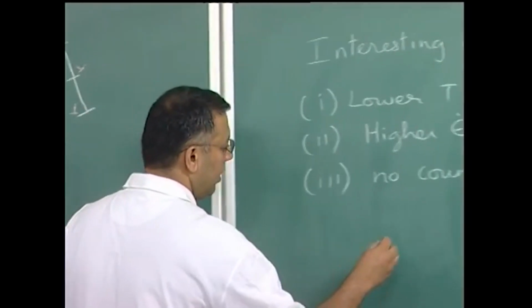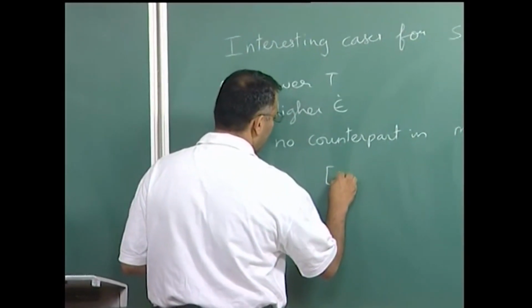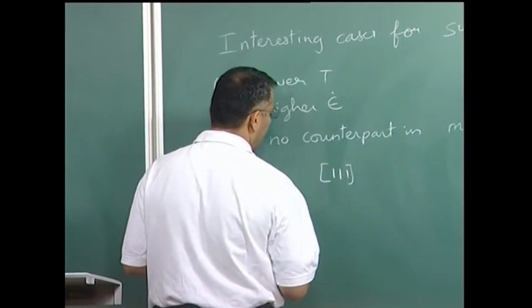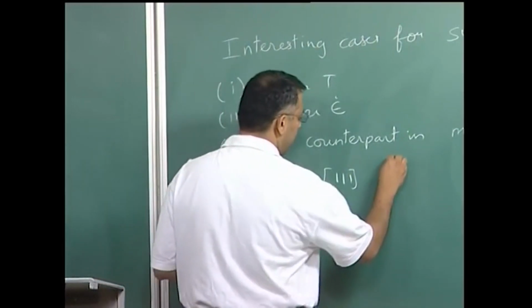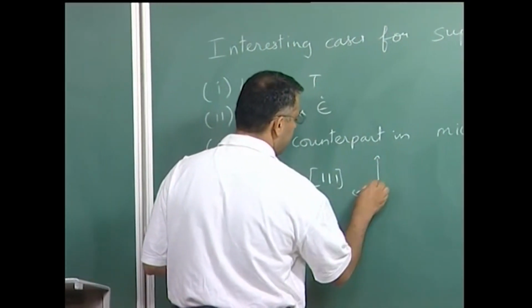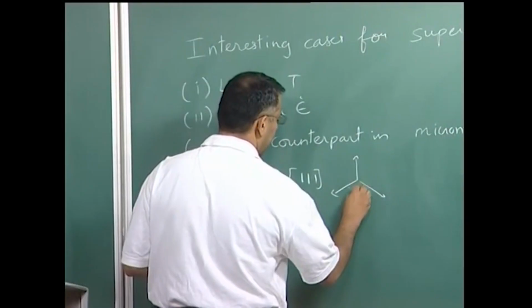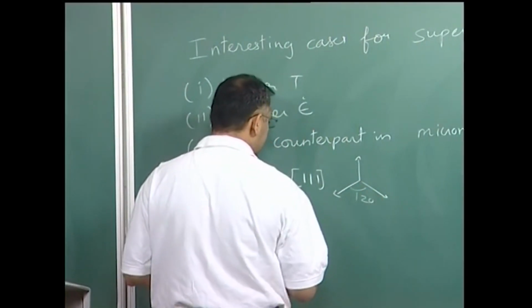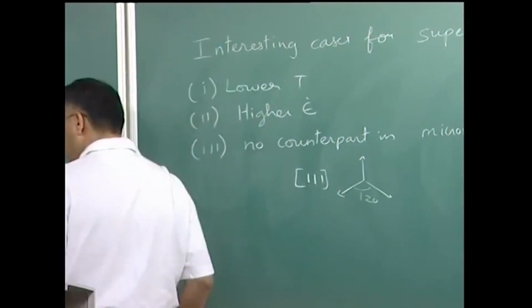As you know, in BCC materials the Burgers vector is along the 111 direction, and the screw dislocation actually splits, the core of the dislocation splits along three directions which are 120 degrees apart. Now, of course, this kind of splitting implies that if the screw dislocation has to move, then the core has to collapse and move to a new plane, and this implies that the Peierls stress for motion of screw dislocations is very large.